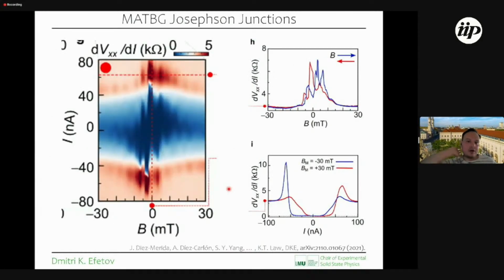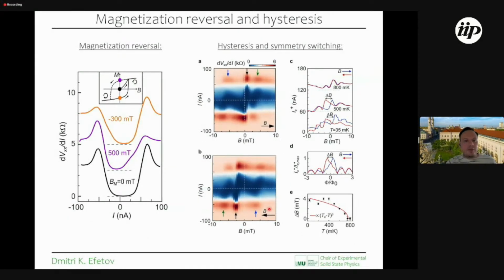And basically, if we zoom in on this Josephson junction, we can really see how strange it is. So first of all, if we take line cuts at a fixed current as a function of magnetic field, then we can see in the dV/dI versus field signal that there is a really strong dependence on the direction of the magnetic field. Sweeping up, we get a certain Fraunhofer interference pattern. Sweeping down, we see that the Fraunhofer interference pattern switches, so it's antisymmetrized somehow, and it is also phase shifted. The same thing we observe for dV/dI as a function of current, when we premagnetize the sample to positive 30 millitesla or negative 30 millitesla: we find that its polarity changes and really switches. So how can we now understand this?